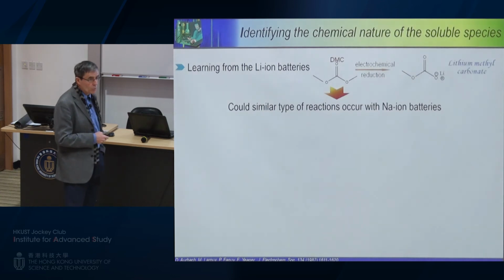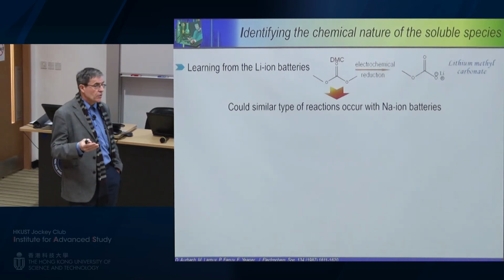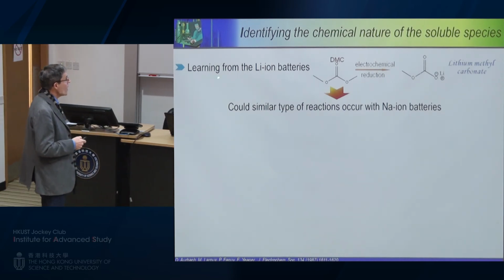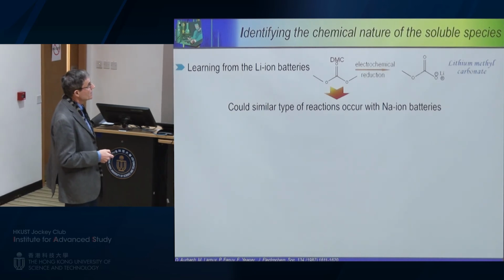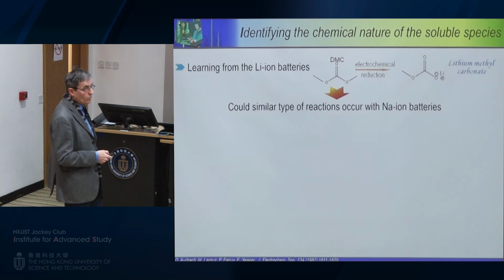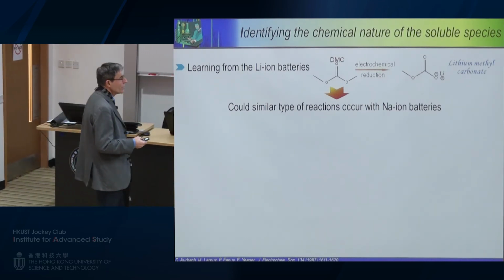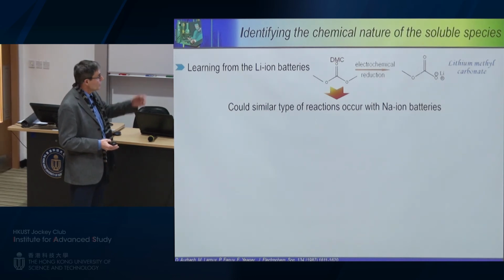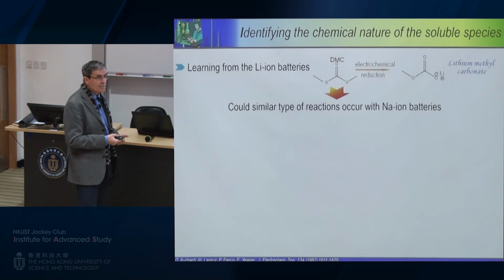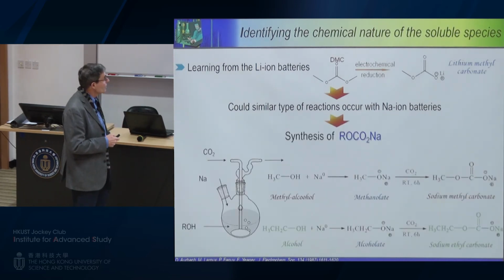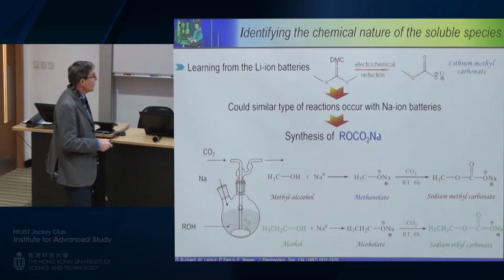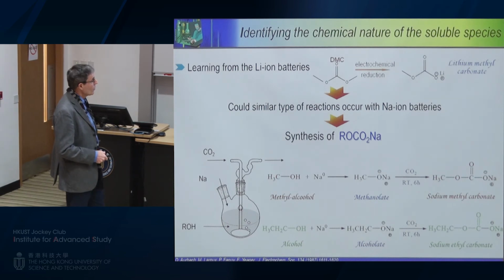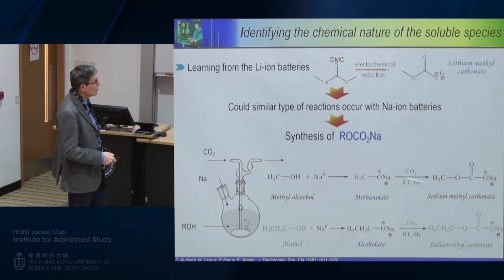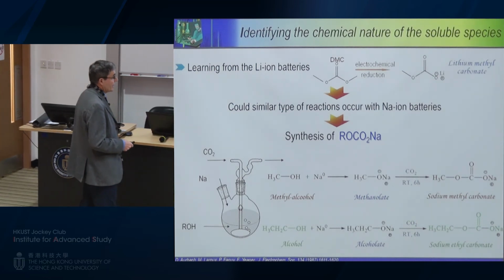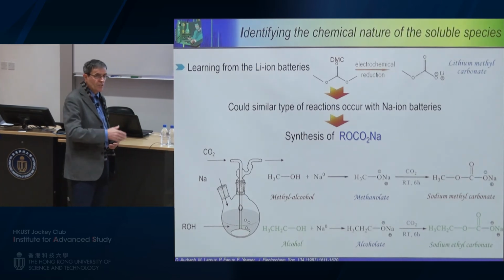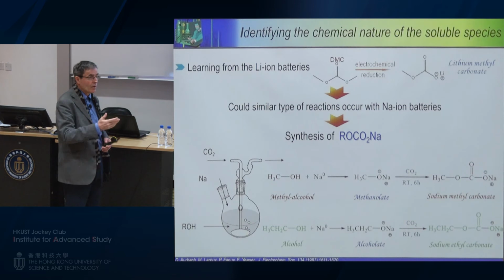Here, we go back to the same systematic that we have been using 15 years ago on lithium ion, and we know from the work of Aurbach and others that the carbonate decomposes into this kind of lithium methyl carbonate and so on. So we hypothesized at least that similar reactions could happen in sodium-ion batteries. To do this, we are obliged to synthesize these model compounds to use as a reference. So we went back to organic synthesis, and we prepared this alkyl carbonate by the reaction indicated here, when you react sodium metal with methyl alcohol to get this methanolate and so on. So we prepared this type of compound, and then now we have our reference to check the signature, both cyclovoltammetric as well as by UV.